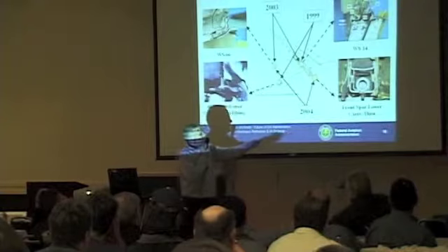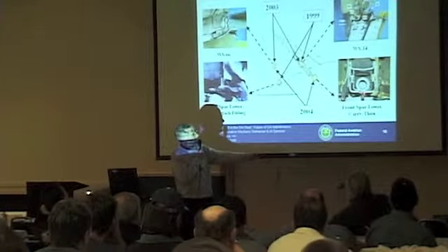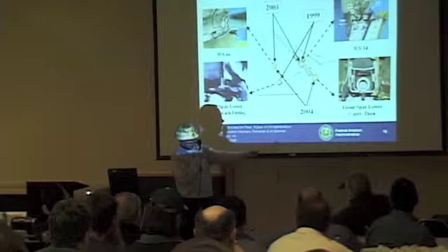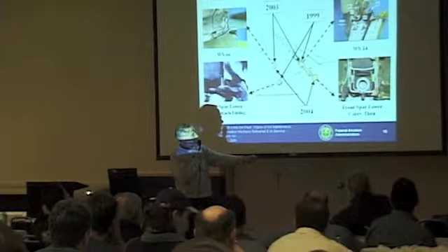Because there's a bit of an issue. The question they have is, we can inspect this area here. We can inspect this inner channel. They can come in through what they call the mouse hole, come up in here, and do an eddy current inspection of these fasteners right here, go around those fasteners. But the outer channel is uninspectable.